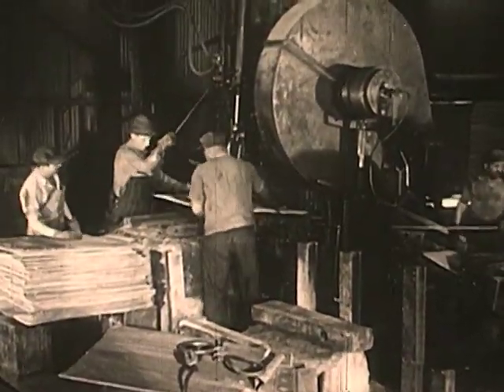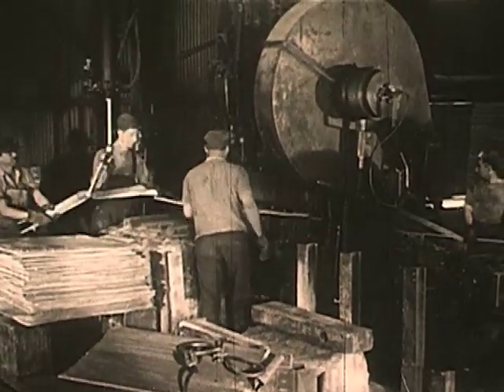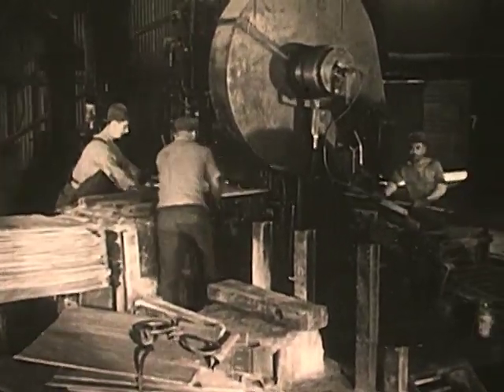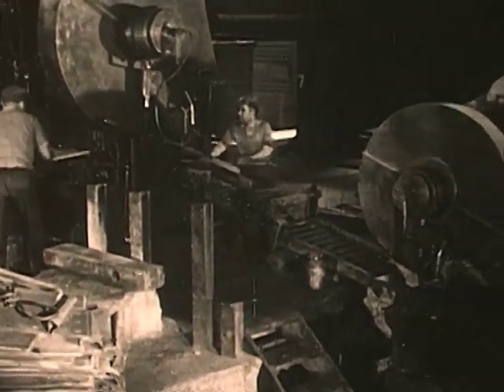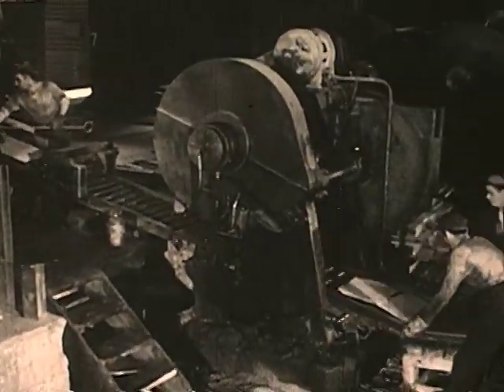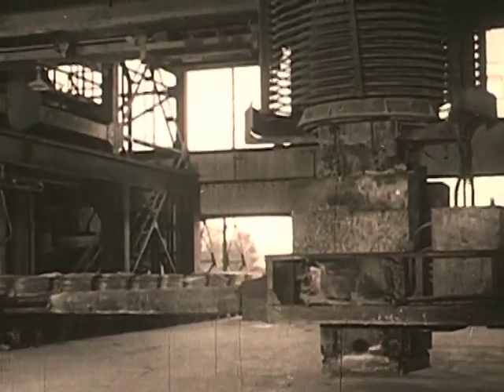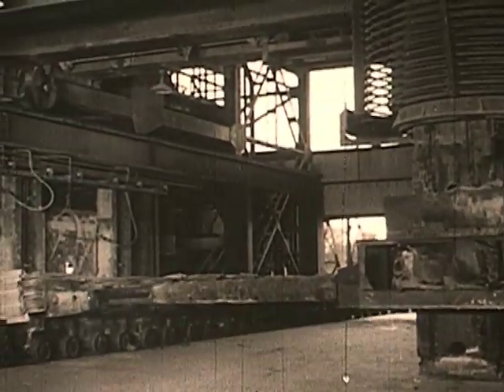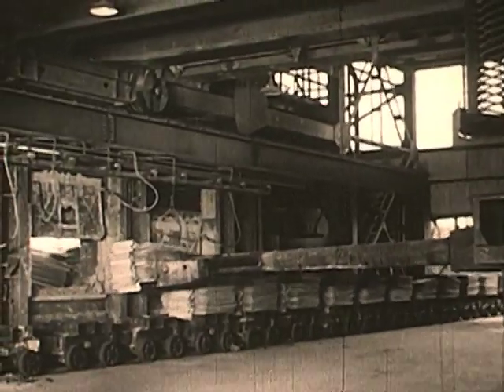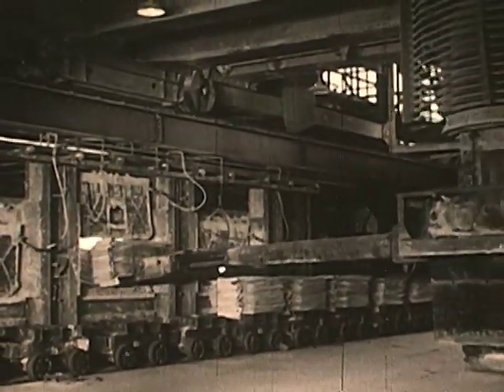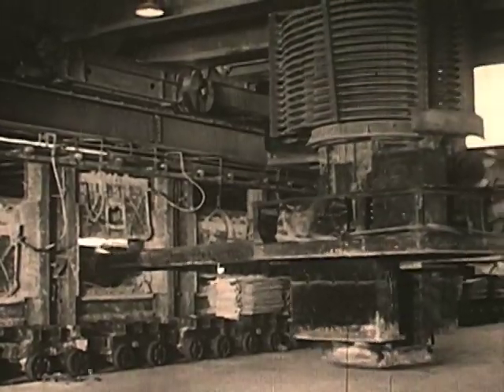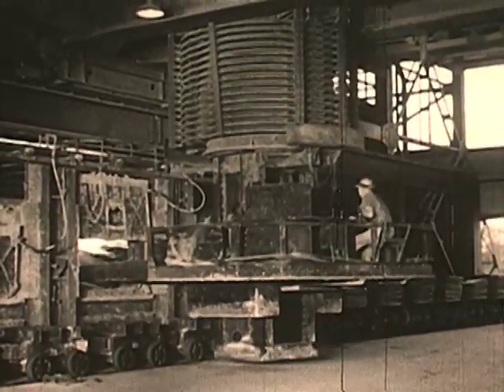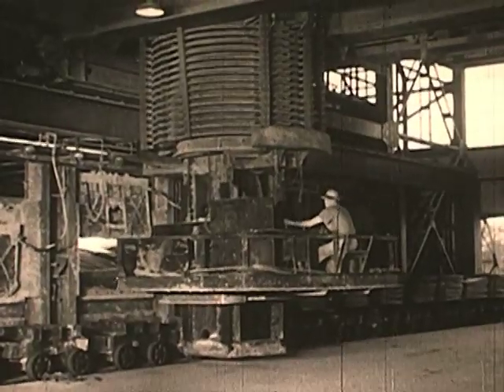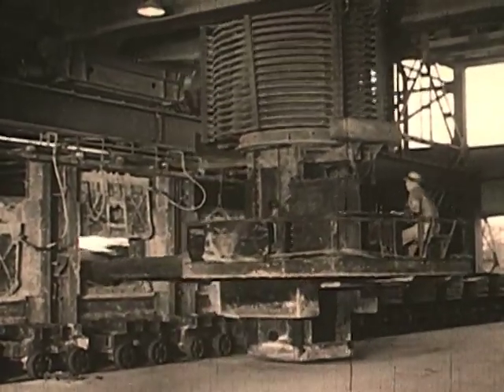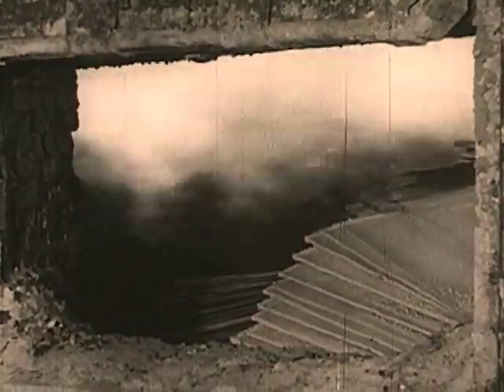Some of the copper cathodes are sent to the shearing department where they are cut into sizes required by the United States Mint or by brass foundries. Some of the cathodes are taken to this casting department. The charging crane handles 7,000 pounds of cathodes at once and transfers them to a furnace for melting. The furnace is charged with 400 tons of copper once every 24 hours. Natural gas is used for fuel. The inside of this furnace is at a white heat.